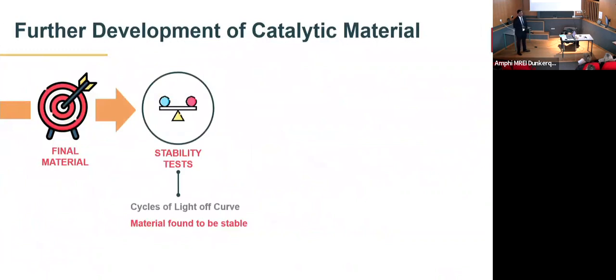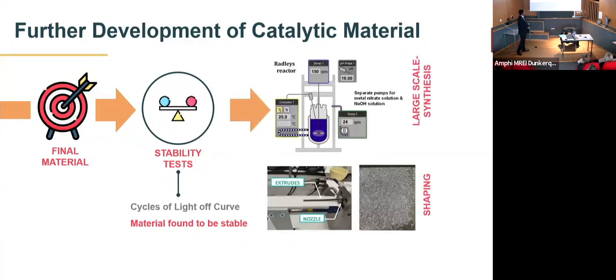So we did cycles of light-off curves between 50 to 400 degrees Celsius, and saw the change in the catalytic activity, notably the NO reduction yield, the CO conversion, and NO oxidation yield. And we found that the material was quite stable under the conditions that we proposed for the stability test. And then upon passing through the stability test, we used the material for a large scale synthesis because we are going to use it for a semi-pilot application in the future work.